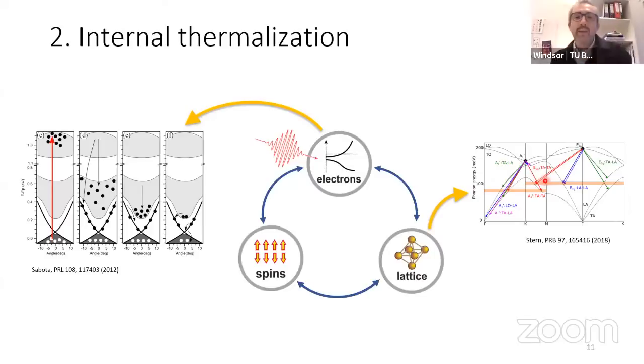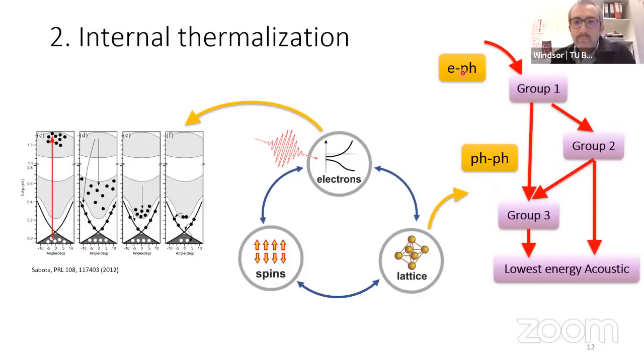And if I then make this in a slightly more cartoonish fashion, which helps us to understand, I would draw something similar to this. So here I've broken down the phonons into a number of groups, where we have an initial group here that is highly coupled to the electrons. So this is electron-phonon coupling. This is, of course, a cartoon. And then we have phonon-phonon scattering events, which describe how the energy flow is not only into the phonon system, but also within it.